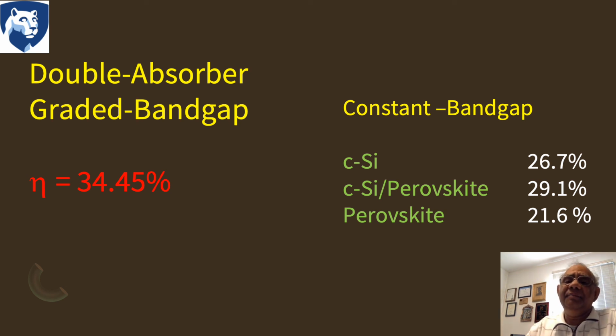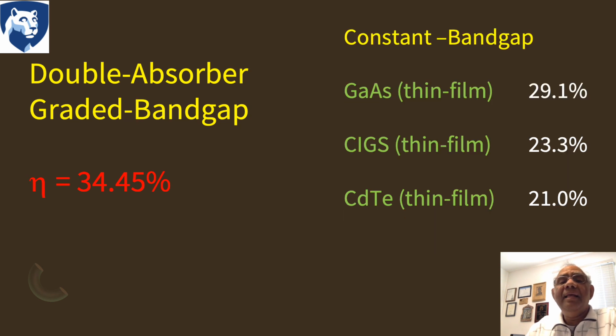Crystalline silicon has an efficiency of 26.7%, perovskites 21.6%, and their tandems 29.1%. Gallium arsenide is the best thin film solar cell. With a constant band gap, the efficiency is 29.1%. CIGS has 23.3% and CdTe 21.0%.